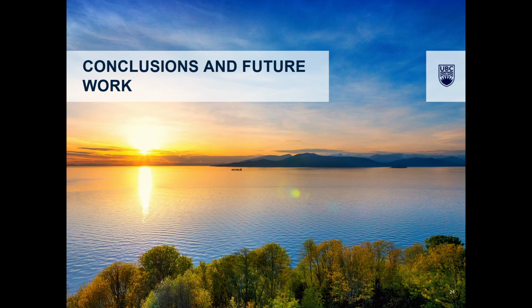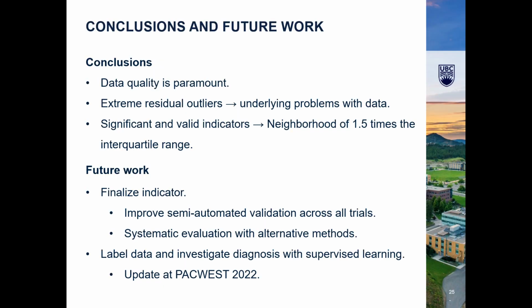Okay, now I will provide some concluding remarks and some future ambitions. The most significant takeaway I have from this work is that data quality is paramount. Many industrial processes have large quantities of data, but big data is not necessarily good data. Even after cleaning our data, we face problems with extreme residual outliers caused by intermittent camera obstructions. Instead of being able to simply sample the largest residual values, we had to determine a significant and valid range which was around 1.5 times the interquartile range.